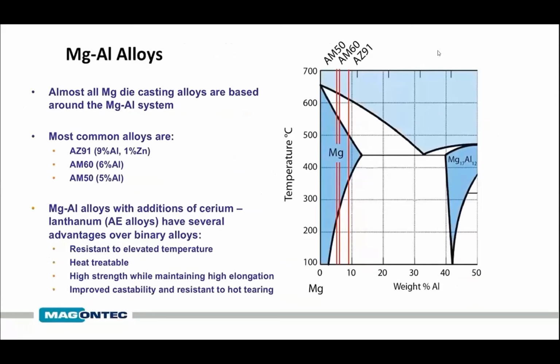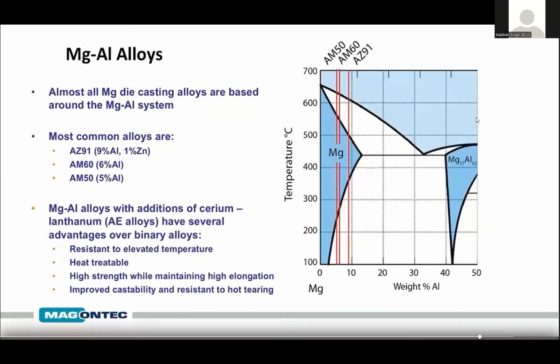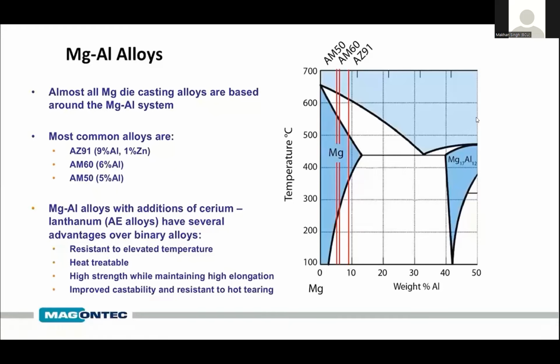Die casting alloys are based on the magnesium aluminium system. The common alloys, AZ91, AM60, and AM50, have varying amounts of aluminium, and in the case of AZ91, some zinc for additional strengthening. Magnesium aluminium alloys with additions of rare earths, the cerium and lanthanum rare earths called AE alloys, are emerging as alloys with several advantages: resistant to high temperatures, heat treatable. They give a very good combination of strength and ductility, and have very good castability and resistance to hot cracking.